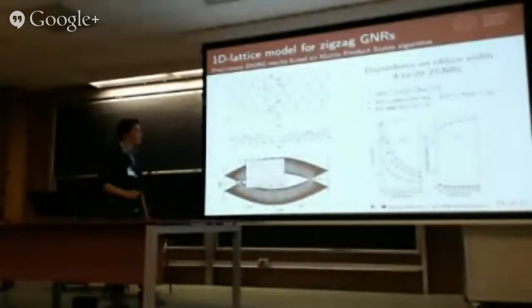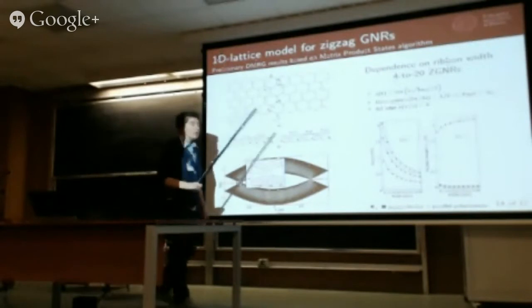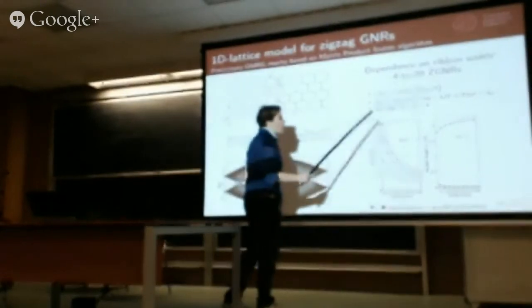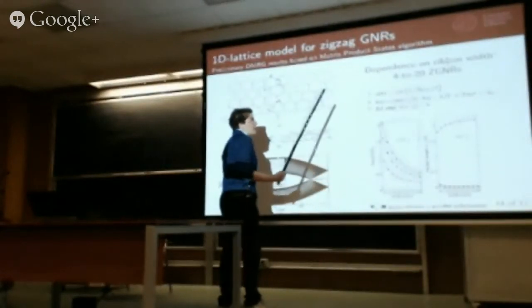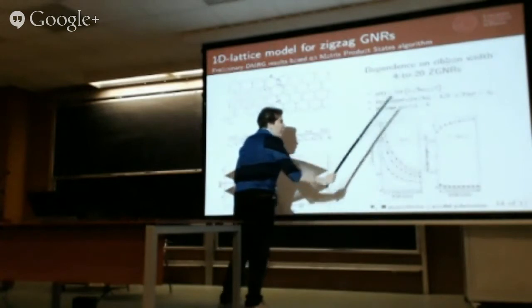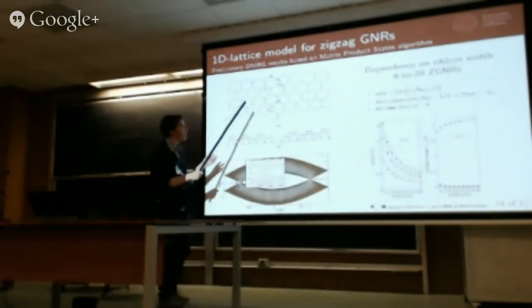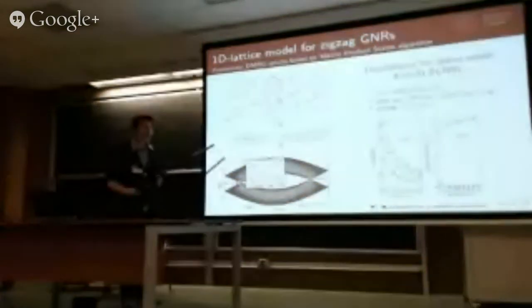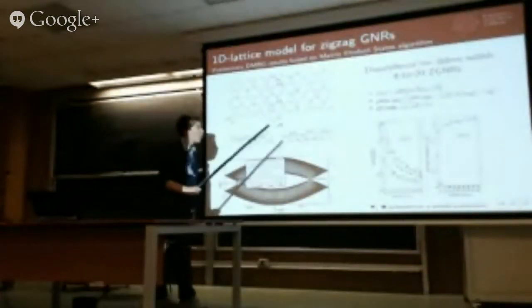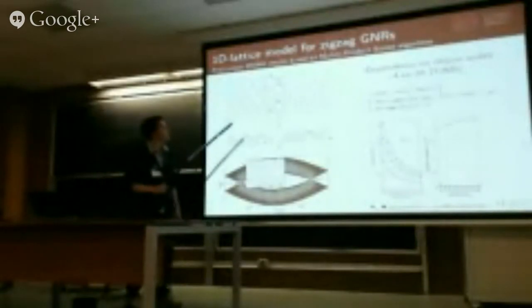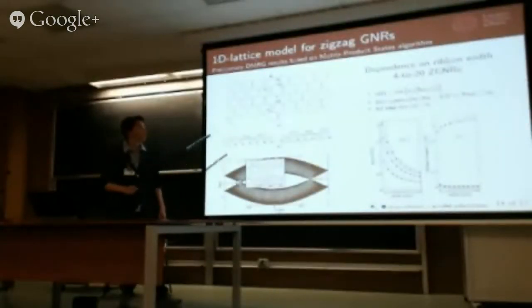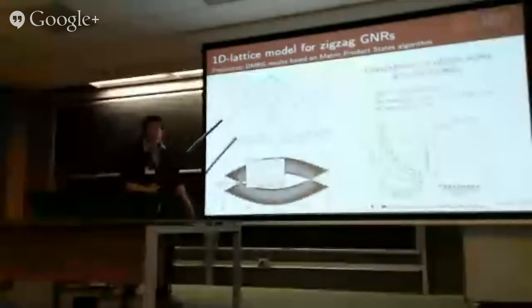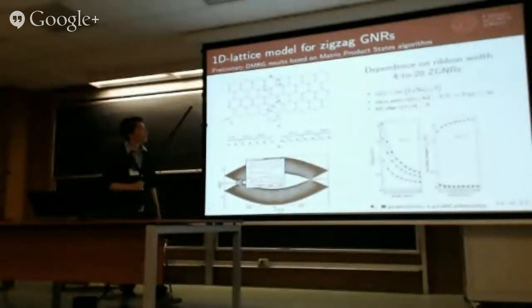At the Dirac point, where there is the onset of edge states, we can see that C becomes equal to 1, so the model greatly simplifies into an open-ended chain with uniform hopping everywhere. So this is quite convenient also for performing density matrix renormalization group calculations, since this algorithm best converges for one-dimensional systems with open boundary conditions.